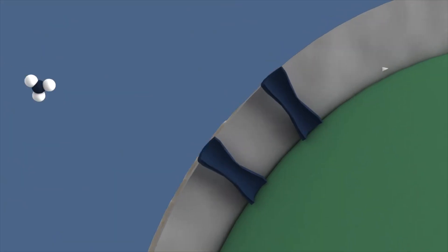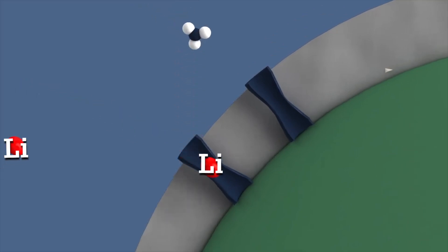Sometimes the most obvious numbers can be misleading. Let's be specific and look at the process picked by Eramet in Argentina for the first ever end-to-end DLE plant. To produce battery-grade lithium carbonate, they rely on an alumina-based adsorbent that holds the lithium as brine passes over it, and releases it when you backwash it with fresh water.